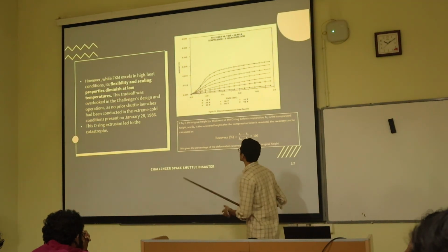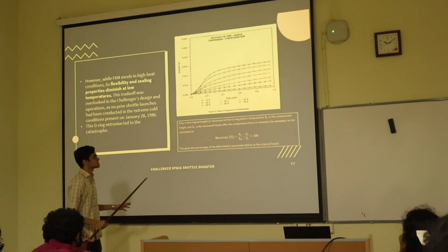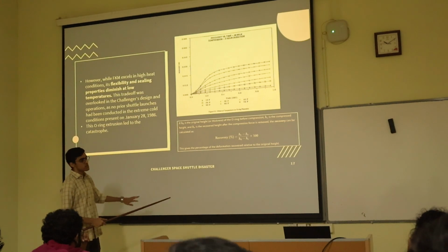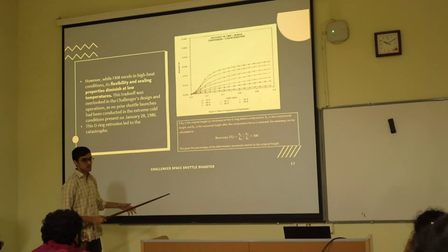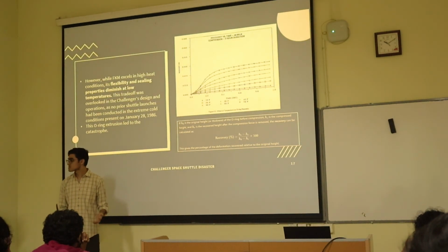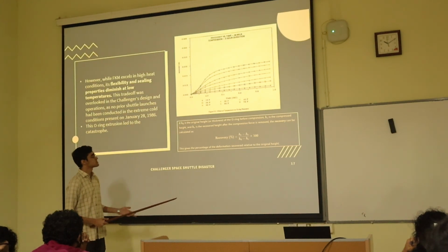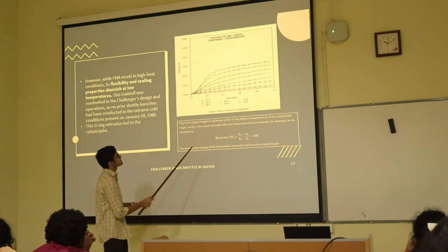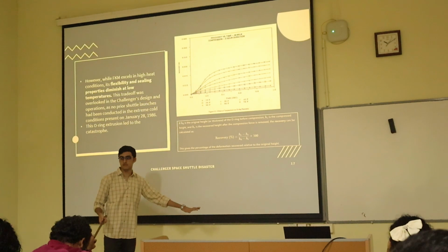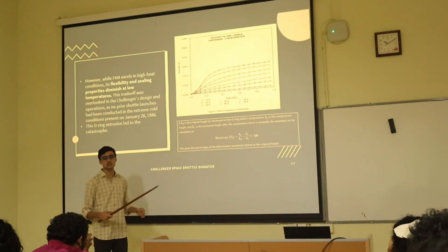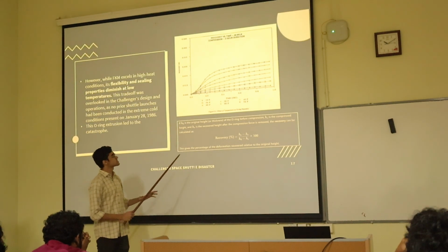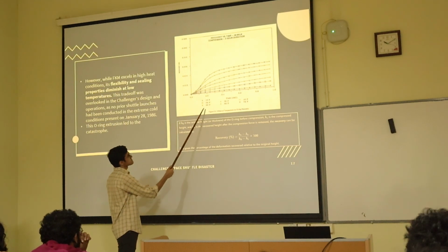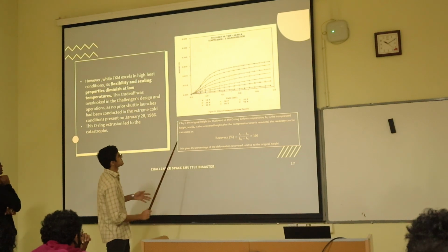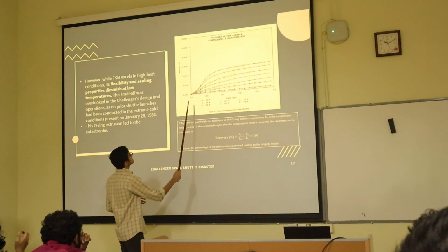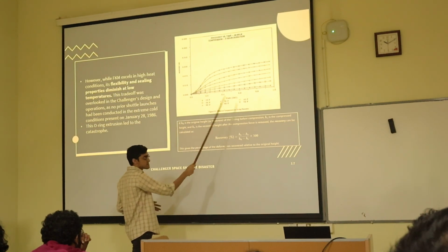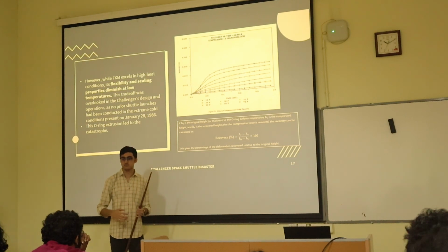Now I'll talk about recovery time. At higher temperatures the recovery time is pretty low, but at lower temperatures the recovery time is higher. As you can see, at lower temperatures the recovery rate is even lower, because of what I said before. The relaxation time is so high at lower temperatures that the recovery rate is very low. And that is what NASA eventually figured out for the FKM O-rings: at different temperatures they saw the recovery rate, and at higher temperatures the recovery rate was higher, while at lower temperatures it was very low because of the relaxation time.